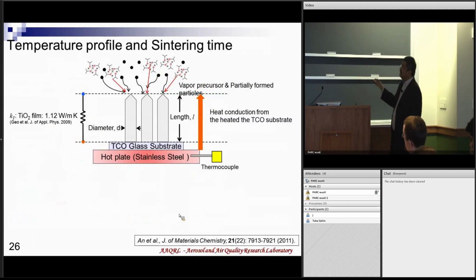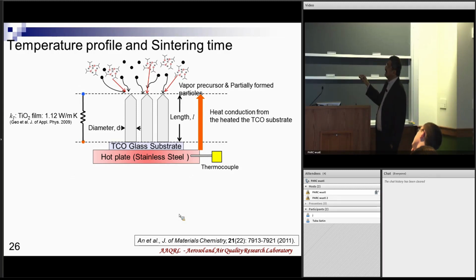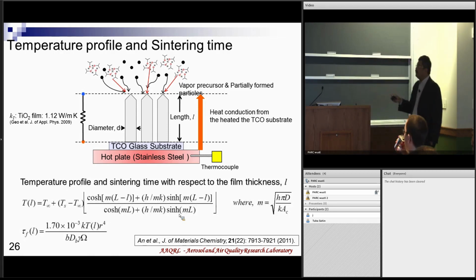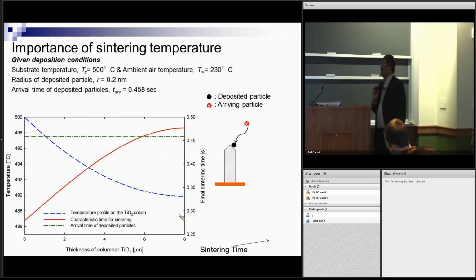But something rather interesting begins to happen. I want these to grow to a sufficient length so I can really use it effectively as a device, and because of the heat transfer, the upper regions start cooling down, because this is hot now and this starts cooling down, and those characteristic times change. Again, I can do heat transfer calculations. I'm not going into all those in detail, and I compare the different characteristic times, the sintering time with the arriving time and so forth, and you can see that I reach a condition where this is now cool enough that this particle is not going to sinter with this. It's also a small particle sintering with a relatively large structure, so this becomes a slow process.